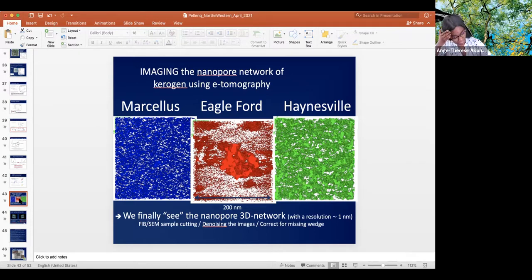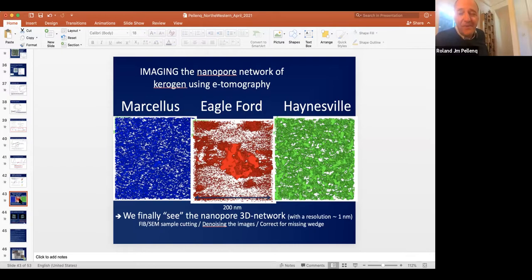Mm-hmm. That's a really good point. I have a follow-up question. At some point you're saying that for CO2 sequestration, we can use CO2 to replace methane, suggesting that if we integrate CO2 sequestration and shale extraction, that would be efficient. But when we look at CO2 sequestration, what we see is that the CO2-saturated brine actually alters even the nanostructure. For the clays, for instance, there's this issue of swelling of the clay because of CO2-saturated brine. So how do you take that into account?